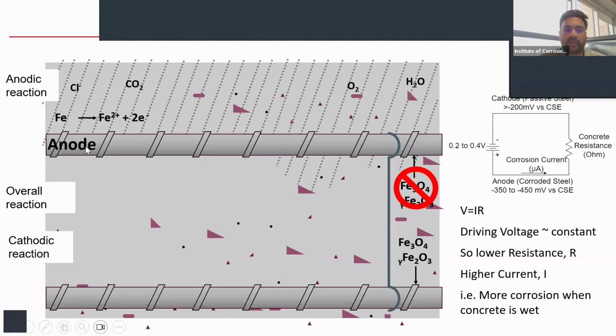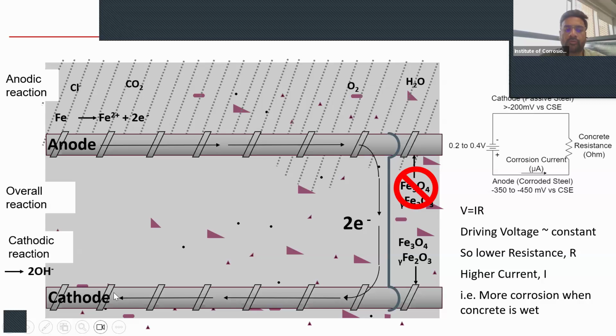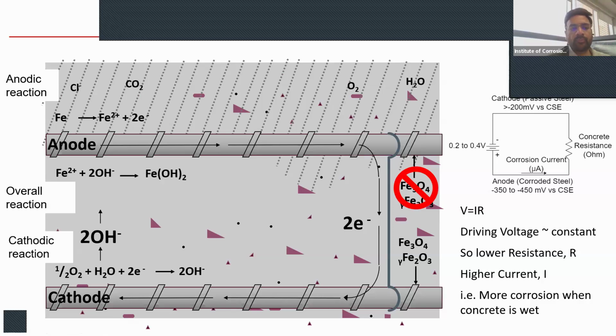As a result, an anodic site is formed on the steel bar, through which electrons travel and reach the cathodic side of the steel bar, which reacts with water and oxygen from the environment and pore water to form hydroxide ions. These travel back to the anode and cause formation of ferrous hydroxide, which on subsequent oxidation causes ferric oxide, that is the rust, on the anodic part of the steel.